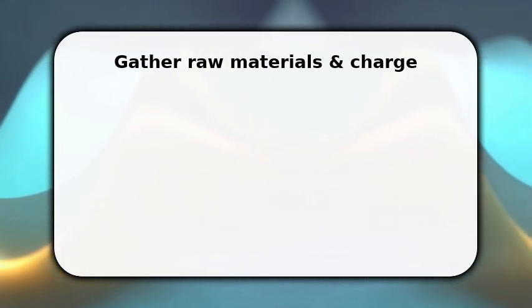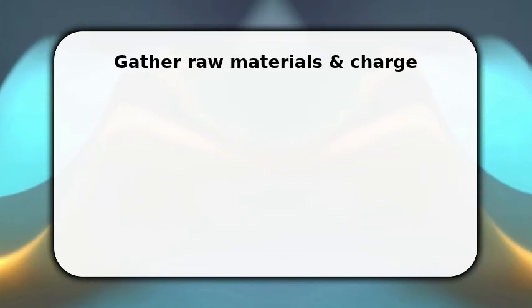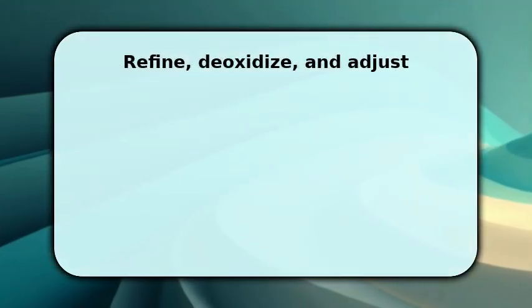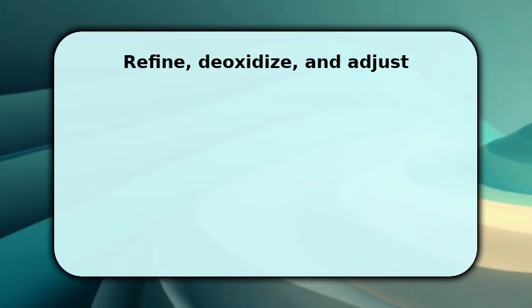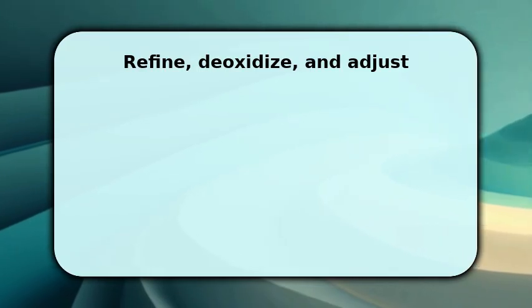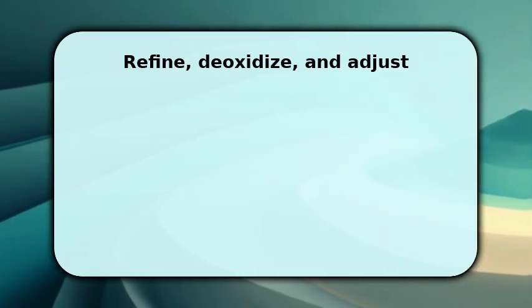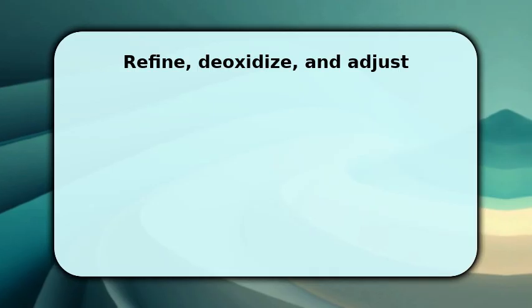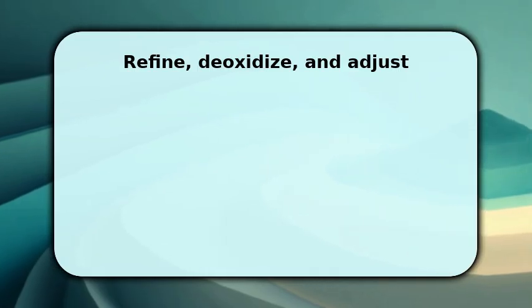Once the melt is fluid, you refine by blowing oxygen to strip carbon and oxidize impurities. This controls corrosion resistance later. After decarburization, add deoxidizers and ferroalloys to correct oxygen and sulfur levels, and then add chromium, nickel, and other elements